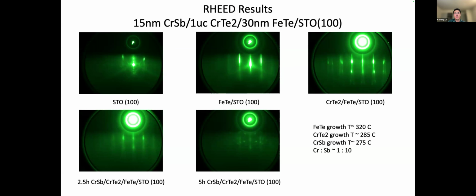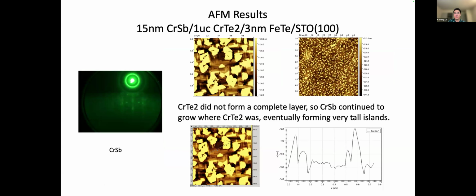The RHEED pattern suggests chromium ditelluride did not fully cover the iron telluride, which led to the chromium antimony nucleating on certain areas which have chromium ditelluride, and it forms tall islands, which means we need to continually optimize the recipe. And the AFM results confirm that chromium ditelluride did not form a complete layer, and chromium antimony grew preferentially on islands, yielding very tall features. The surface roughness is very high in these regions, which is unsuitable for STM measurement.